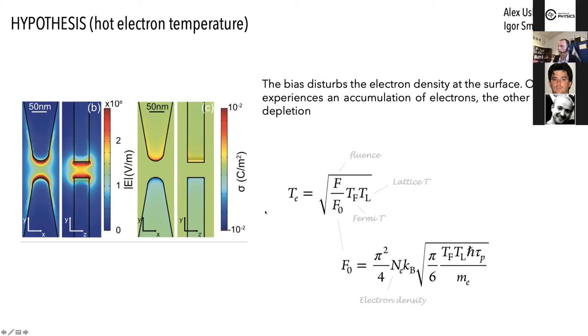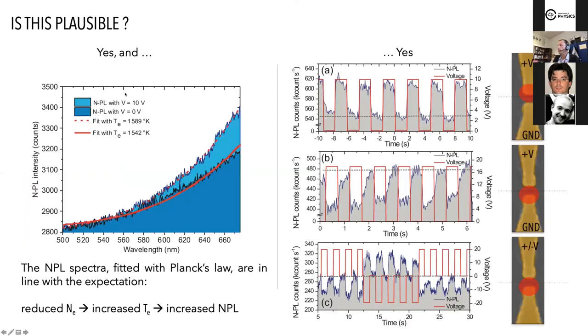And consequently, this affects the electron temperature very locally. And this is a plausible interpretation because this NPL is a surface effect. The electron temperature that is responsible for the emission of the light is at the surface. We're talking about electrons that are located at the surface, and if we locally change their density, it's likely that we're going to change their temperature. And if we change the temperature, the intensity is going to change. So is this plausible? Yes.